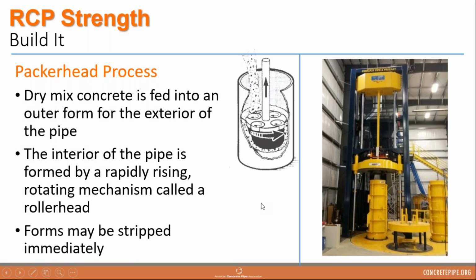All right, so let's look at the packer head machine for casting pipe. This is slightly different than the vibratory process that was just illustrated. The packerhead also uses that dry mix concrete, and it is actually fed into the outer forms, which shape the exterior of the pipe. The interior of the pipe is then formed by a rapidly spinning mechanism called a roller head, and that is raised up through the center of the pipe, and that roller head consolidates and compacts the dry mix into the pipe walls, and then those forms can be stripped immediately.